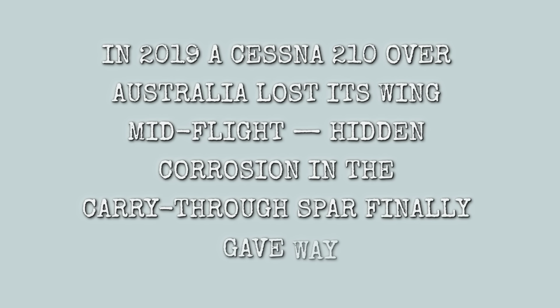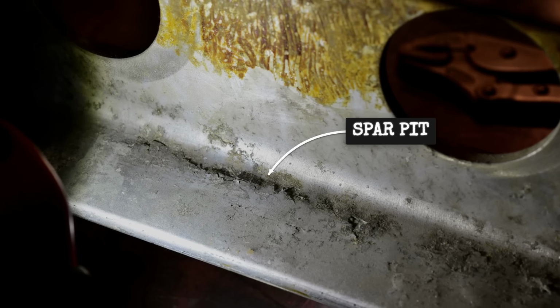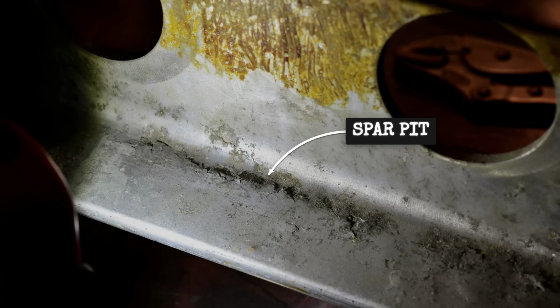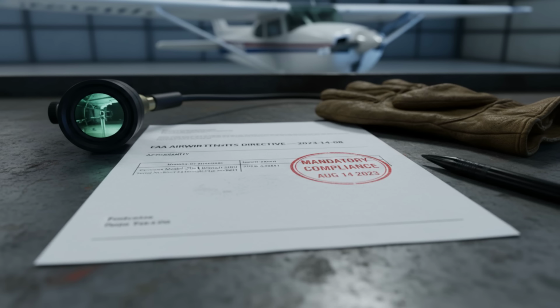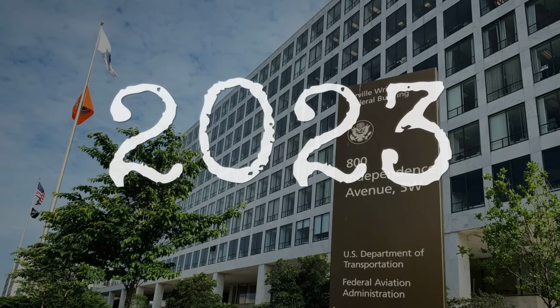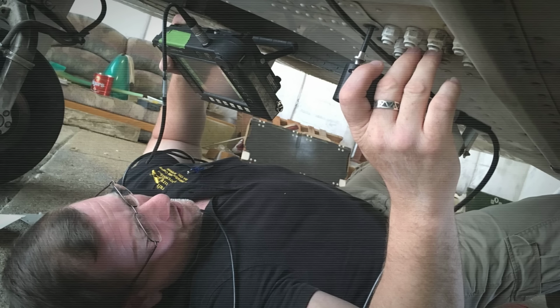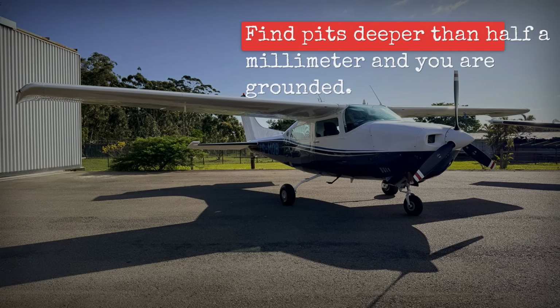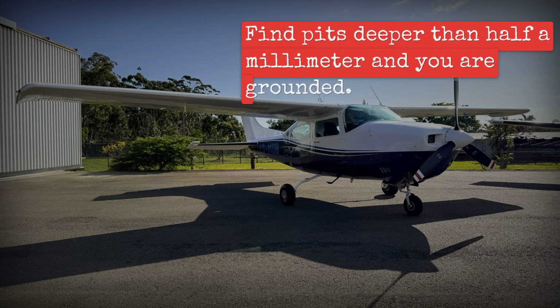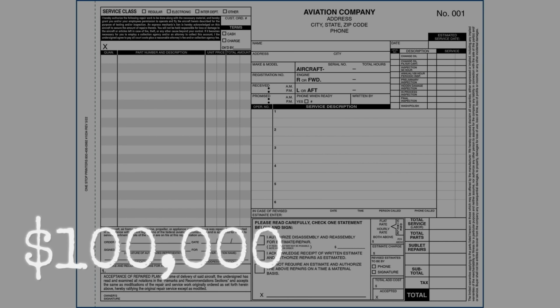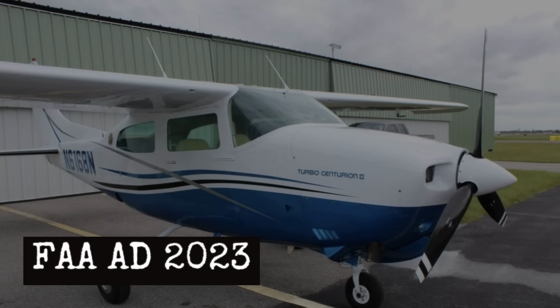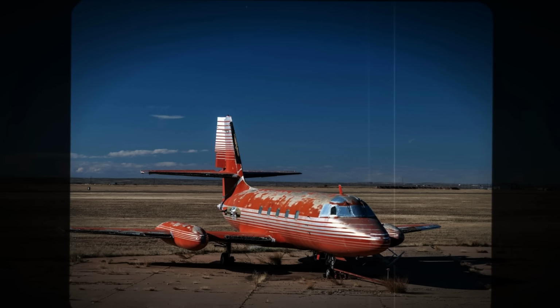In 2019, a Cessna 210 in Australia lost its wing mid-flight after a pit just 1.8 millimeters deep triggered a fatal fracture. The FAA responded with an airworthiness directive in 2023. Every affected 210 must have the headliner ripped out and the spar scanned with eddy current equipment. Find pits deeper than 0.5 millimeter and you are grounded. If the spar fails, replacement can run upwards of $100,000 more than the plane is worth. That is a financial death sentence.